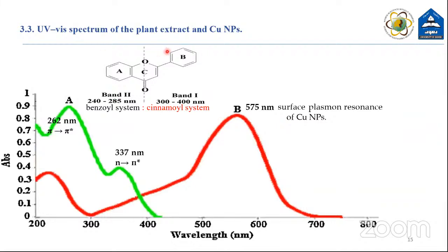UV-visible spectrum of our plant extract. Spectrum A is for plant extract, and spectrum B is for copper nanoparticles. In the plant extract spectrum, there are two main peaks. The first one, band one, corresponds to the cinnamoyl system, at about 337 nanometers, corresponding to the n to pi star electron transition. And band two corresponds to the conjugated double bonds inside the benzoyl system at 262 nanometers. These two bands are in general used as a fingerprint for most of the flavonoids or phytochemicals inside the plant. And in spectrum B, we have the spectrum of copper nanoparticles.